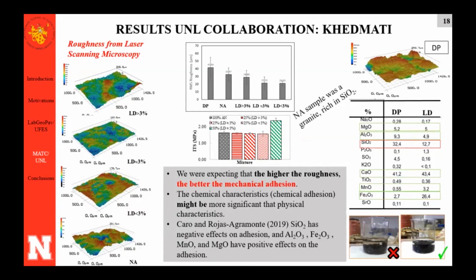And then from the simple boiling test, this slag performed the worst compared with LD. This picture you cannot see very nicely, but it was clear that the DP slag and LD, with the same binder content, passed through this test here, the simplest test that people do to evaluate adhesion between aggregate and binder. This DP didn't have all the particles covered by binder.